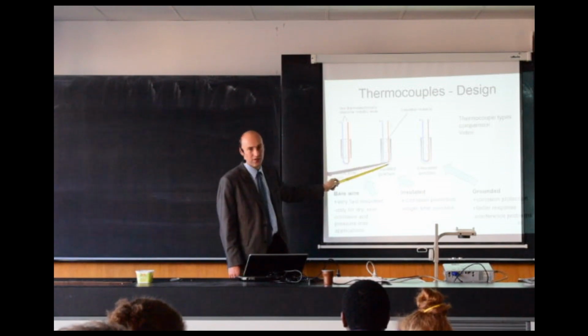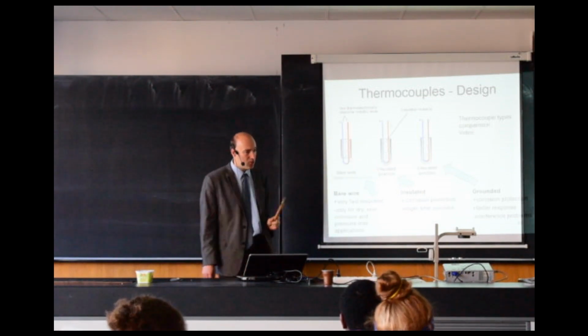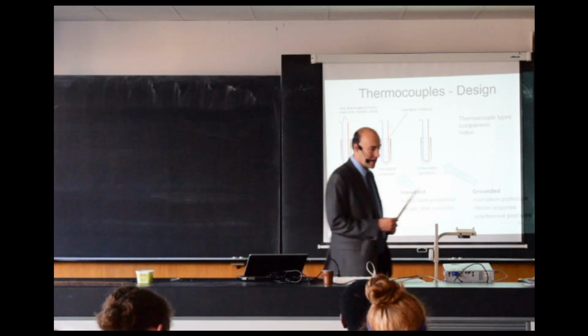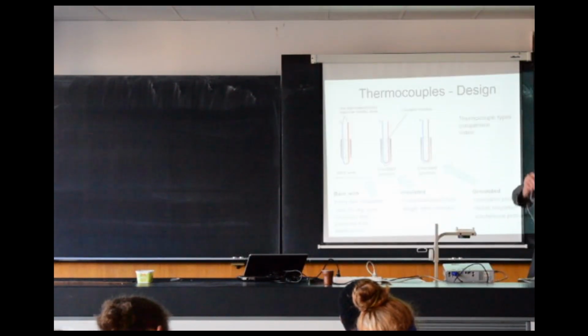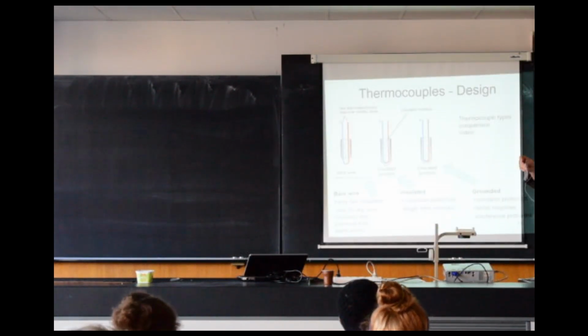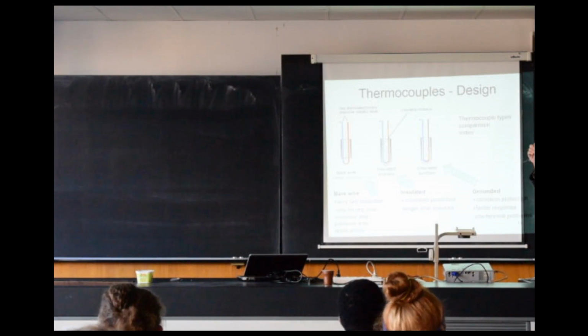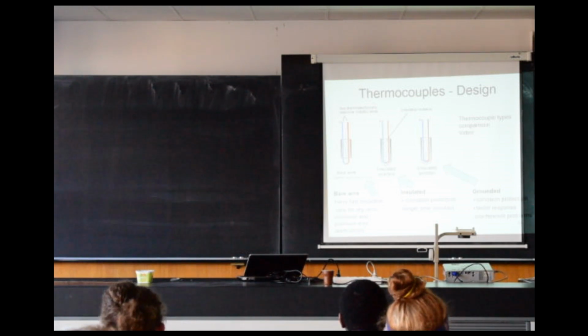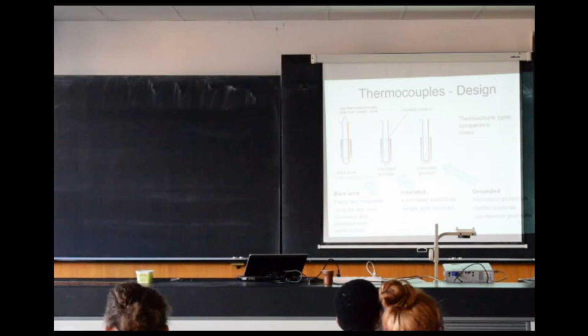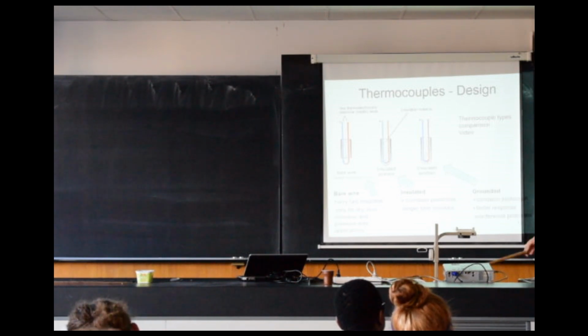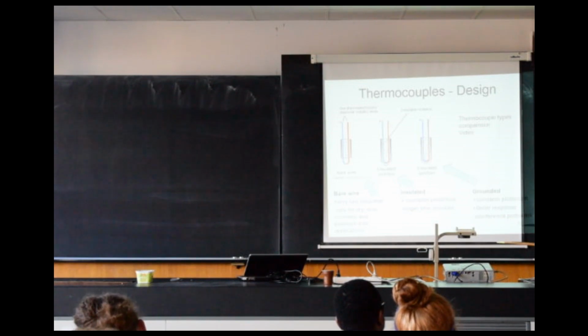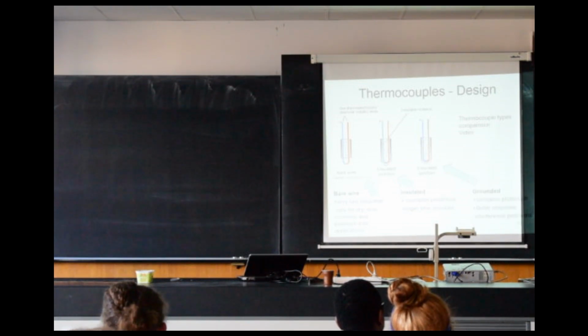Here it depends on the thermal well, but to give you an idea, if I would take a bare wire like this, and use it and measure the time constant, this would have a time constant of, let's say, 1 second. So it will be very fast. If I put it in a thermal well, for example, like this big, it could easily have a time constant of 2-3 minutes. So it protects quite well the thermocouple, but decreases the sampling rate that you can get from the sensor.